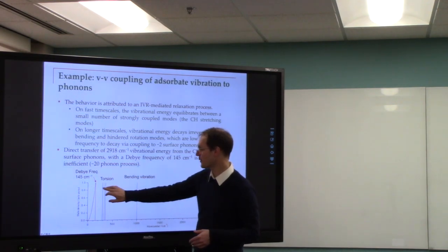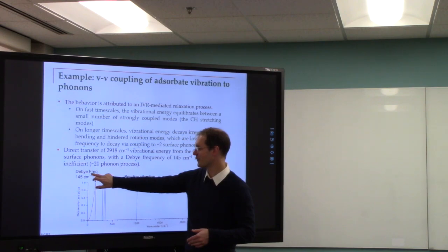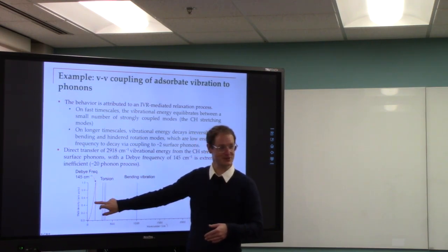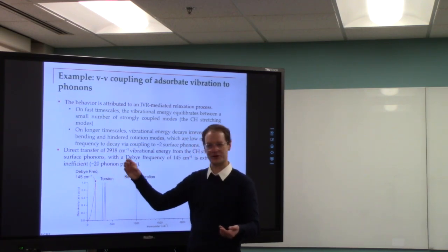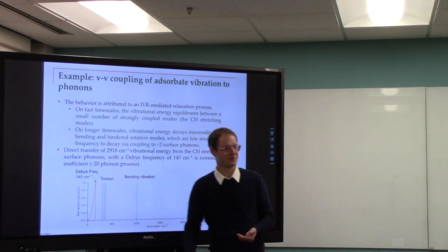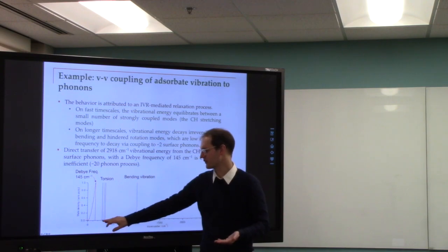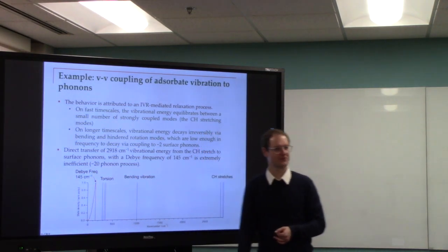These torsional modes can then couple to the phonon modes of the solid via 2-to-1 processes, so you can excite approximately 2 quanta of phonon vibration with 1 quantum of molecular torsion, if the torsions are about 300 wave numbers and the Debye frequency is about 150.